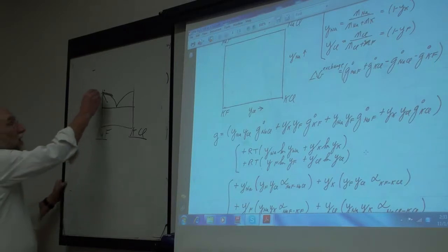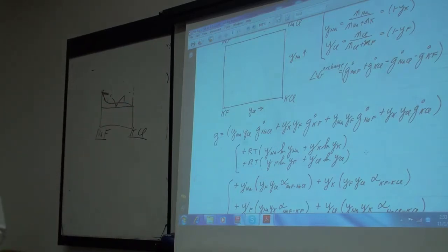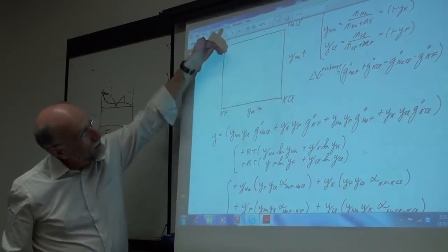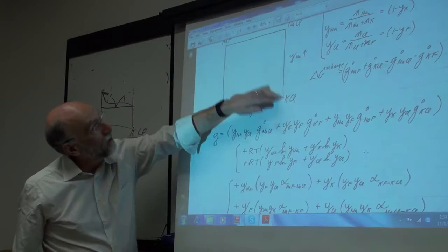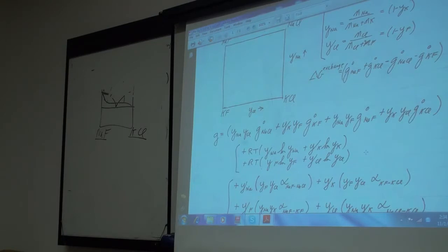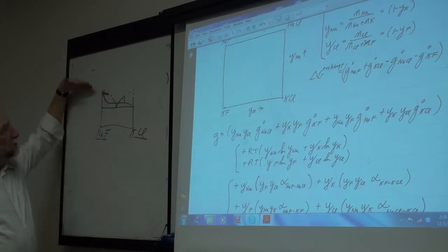So you start off dropping faster, but then you get the positive deviation because of this other effect. Initially, as you start off here, it goes down faster than it would if it was an ideal solution of just molecules, but then you start getting a positive deviation because of the other effect that I mentioned. And this was actually given as the first evidence, back in the late 1940s, that molten salts were in fact ionic liquids with two sublattices: the limiting slope. This is a very easy thing to measure. And whenever you take one salt and you add another salt with a common anion, like NaF-KF or NaF-NaCl, you get a slope up here, all the same.